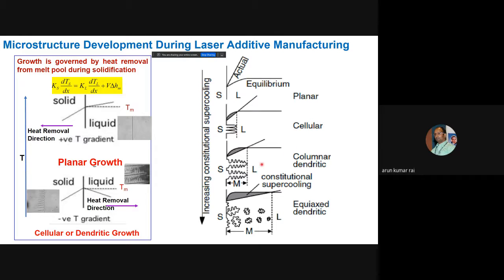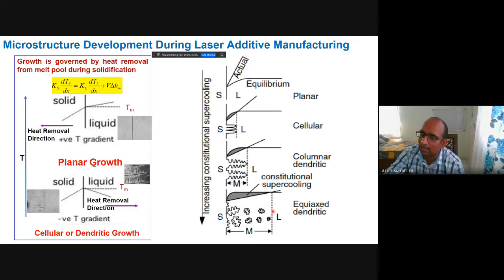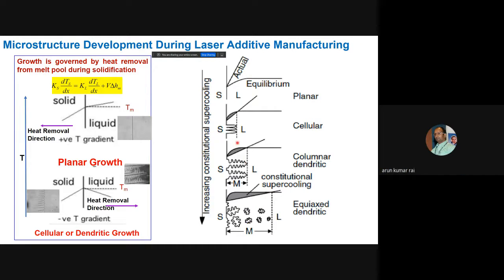And suppose the cooling is still faster, then you will see columnar dendrites, meaning some columns are formed and then arms start forming on them. This arm formation is basically due to the anisotropy of the crystal lattice actually. So the growth happens along certain directions only, which is called the preferred growth direction. So you will see this columnar dendritic structure, but along one line only. And if it is still faster than that, you will see formation of different dendrites. They are randomly oriented, so they are called equiaxed dendrites. So all this microstructure formation depends on your cooling rate. If the cooling rate is very fast, you will have this kind. I will show you that even in a single laser beam profile, you can observe all three structures together.